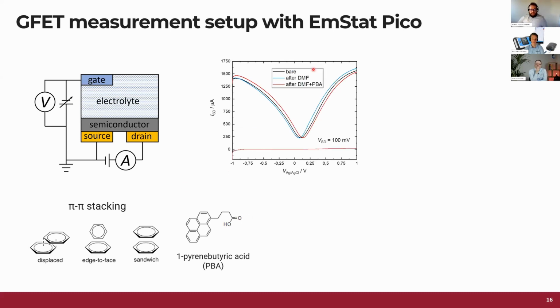The measurement is performed like this in here. This is a transfer characteristic of the graphene device made in a manual manner. We can see the gate voltage on the bottom here and the source-drain current in here. The source-drain voltage is about 100 millivolts. What we do in this experiment, let me go through it with you. So we measure the bare device, which is the black curve.